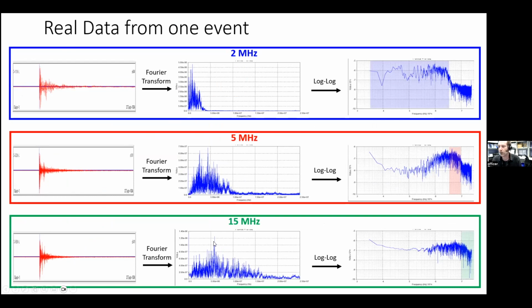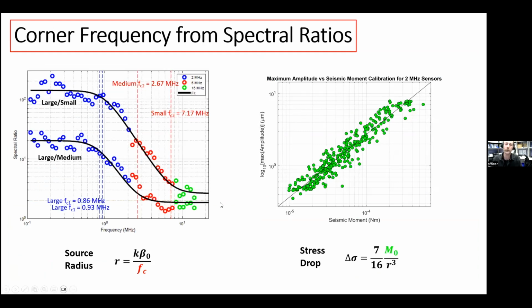And then if you take the log-log of this, you get something that looks like this. So now we can make our frequency spectrum by taking portions of each of these and sort of stitching them together to get an actual frequency response. And then we divide them out and we get these sort of ski hill looking plots we had before. So this is a large divided by a small event. So we go up to the corner frequency of the large event. So we get that.